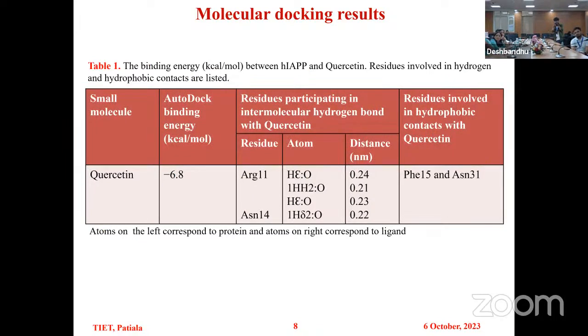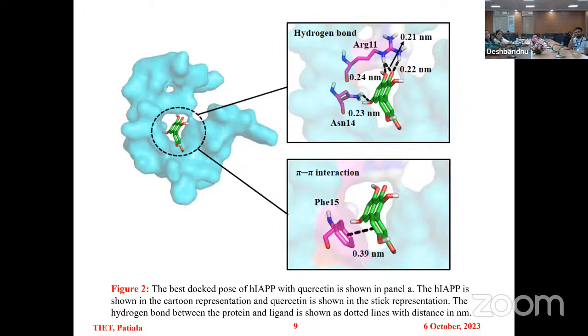Next, we first performed molecular docking studies in order to find the binding interactions and binding energy of quercetin with HIAPP, and it showed a great binding energy of minus 6.8 kilocalories per mole. Arginine 11 and asparagine 14 were involved in hydrogen bond formation with quercetin, and phenylalanine 15 and asparagine 31 were involved in hydrophobic interaction with quercetin. This is the best docked pose of HIAPP with quercetin. The figure shown above shows the hydrogen bond formation, where two residues were involved in hydrogen bonding, and one residue, that is phenylalanine 15, which has been reported to play a major role in the aggregation, was involved in pi-pi stacking interaction with quercetin.